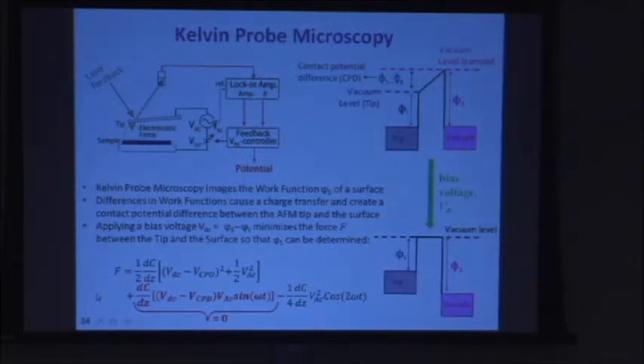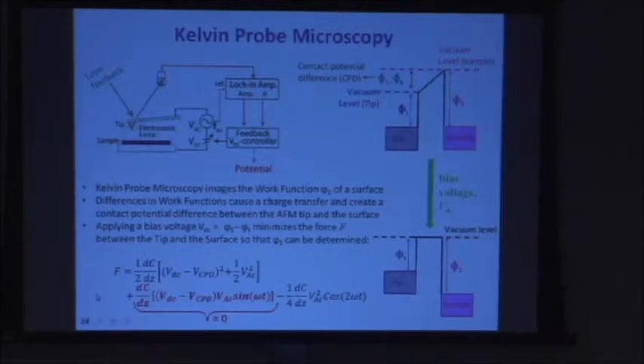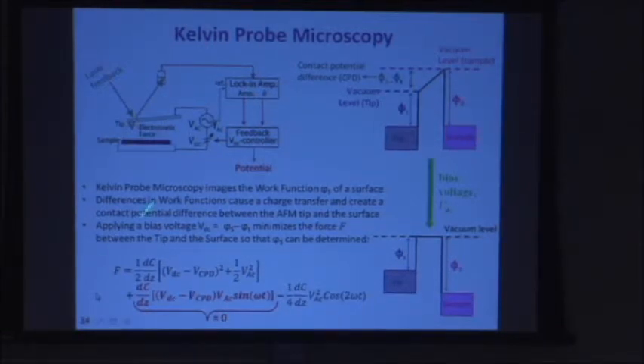One thing that is important is that I don't have contact resistance between this active layer and my electrode. So the work function of these two, the electrochemical potential of these two, has to be more or less the same. A way we study this work function is through Kelvin probe microscopy, a technique that is able to image the work function of a material at the nanoscale. In principle, you can even use conducting AFM if you have a flat surface. You have a probe that has a certain work function, and a contact resistance between your sample and the probe. Locally, you have a diode. From the turn-on voltage of the diode, you know the difference in work function. In principle, if you have a flat material, that works.